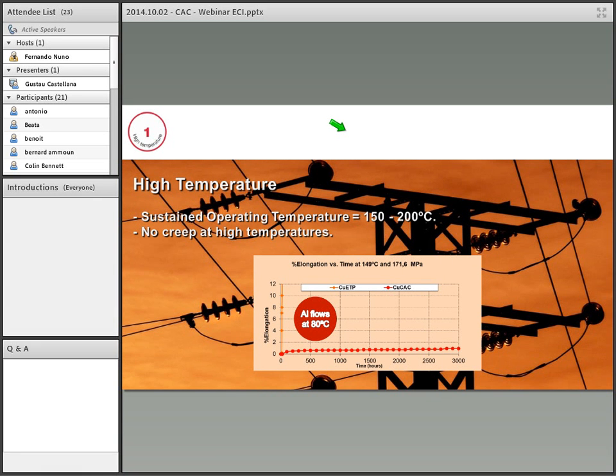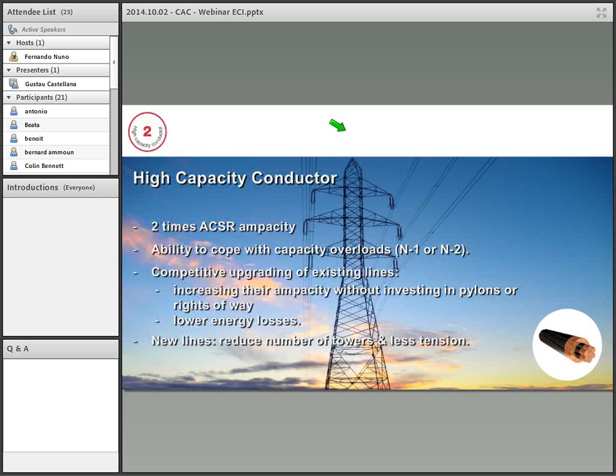And as well, it's important to remark that aluminum flows at 80 degrees Celsius. So with this solution, we can guarantee that with 200 degrees working temperature, there will not be creep. So there will be no loss of mechanical properties. And why is that important? It is important because due to this high temperature, we can increase the capacity of the conductor. So in a normal situation, our equivalent of a CAC conductor can transport 2 times more ampacity than the standard conductor.